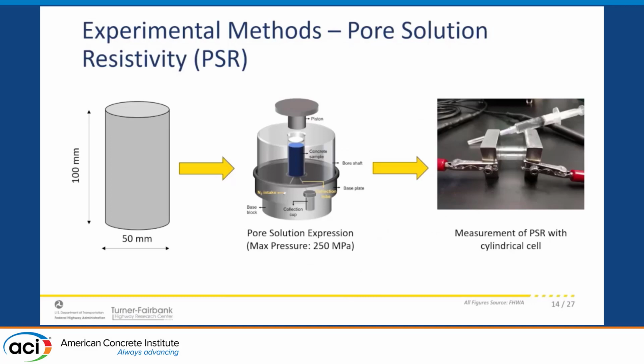We extracted the pore solution from our sample. Again, we were trying to verify the effect of these admixtures on the pore solution, and it's not an easy task to perform. We had a jig at the FHWA labs that allowed us to do that, and then once the pore solution is extracted, we measure the resistivity using this small cell where you basically fill the solution.